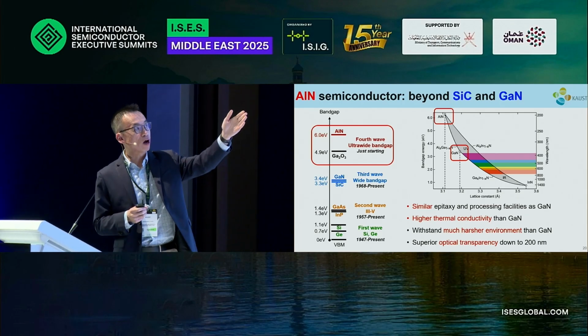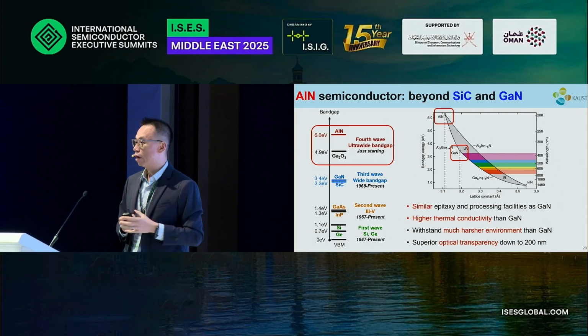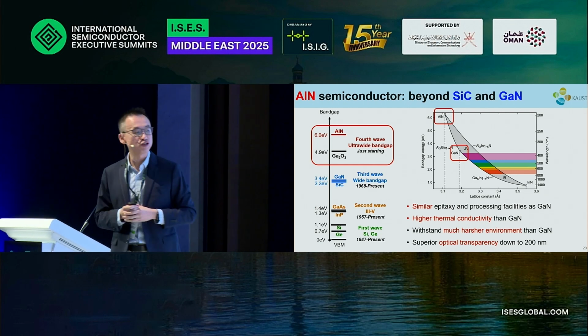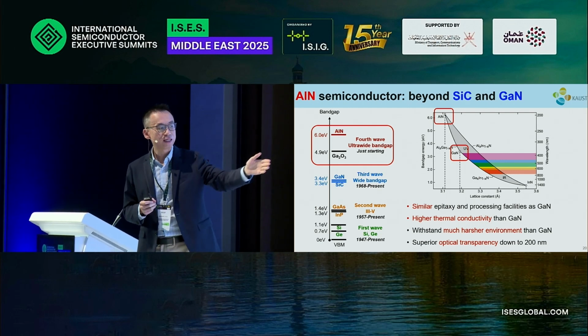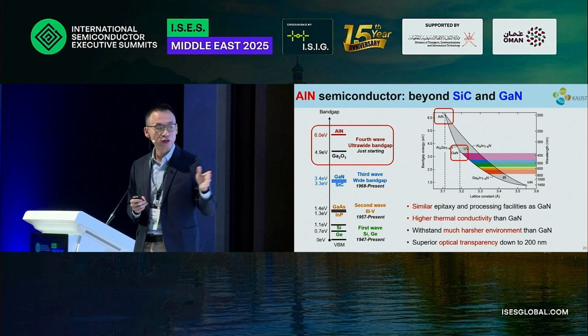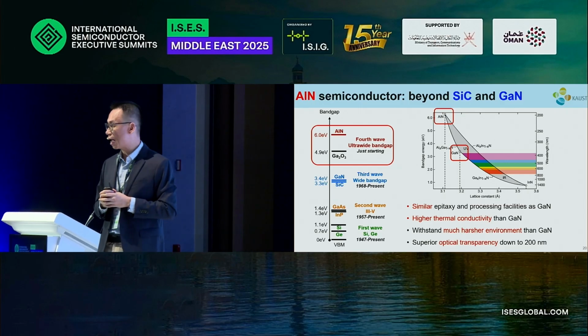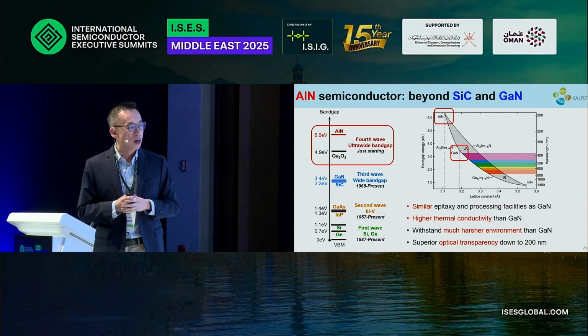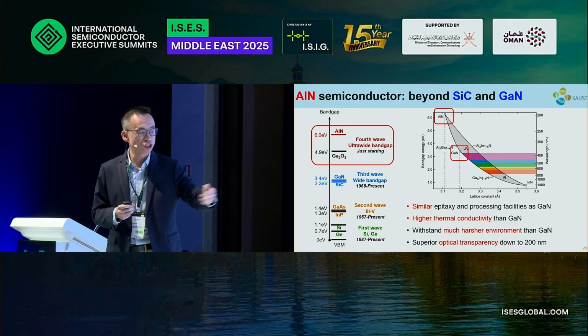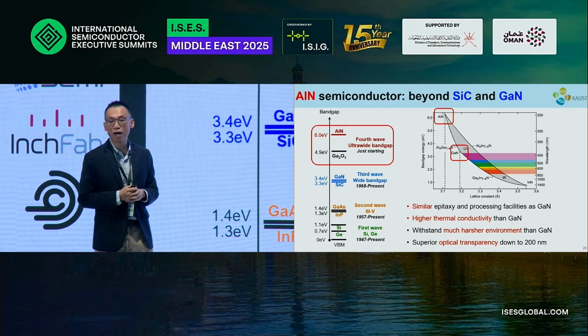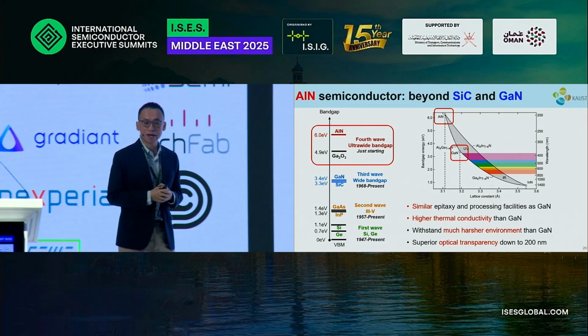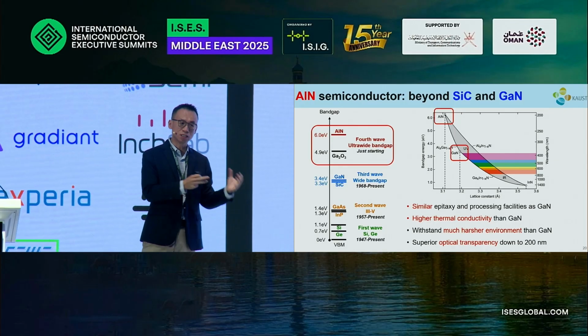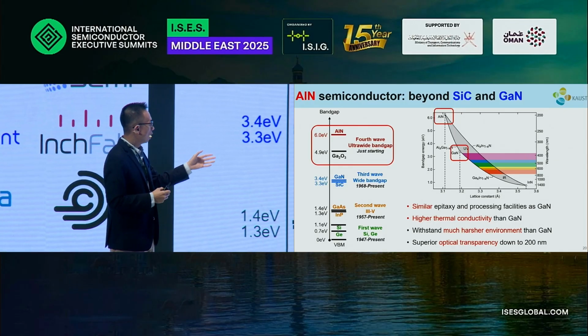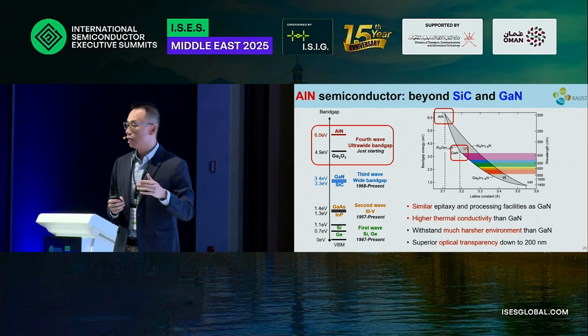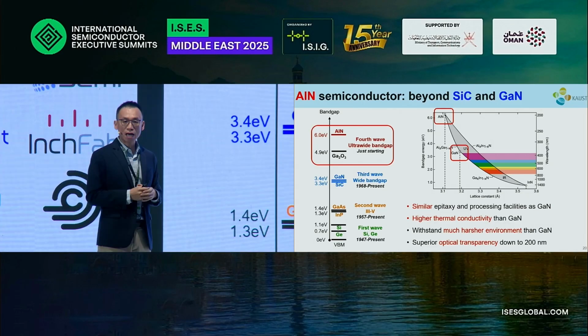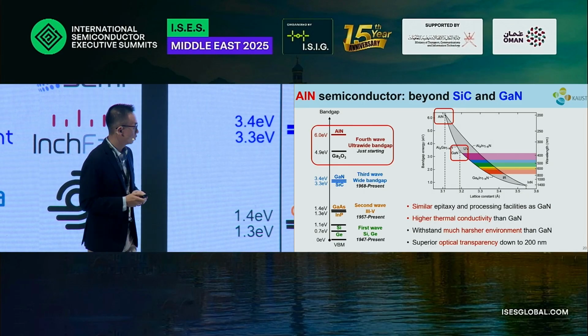So when you switch from gallium nitride to aluminum nitride, you will enjoy similar epitaxy and fabrication facilities. Aluminum nitride also has higher thermal conductivity and can withstand a much harsher environment than GaN because of the much larger bandgap. It can also offer superior optical transparency down to about 200 nanometers. So if you want to integrate electronic devices with optical devices for high-density systems, aluminum nitride has great compatibility with GaN, but also offers additional benefits.